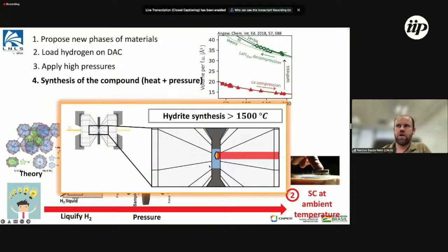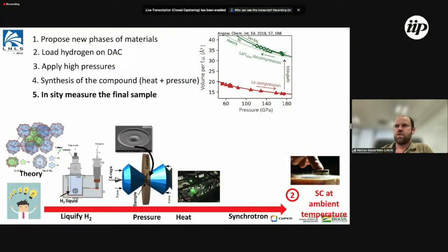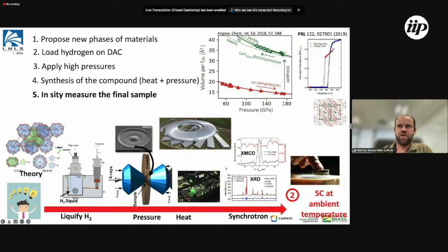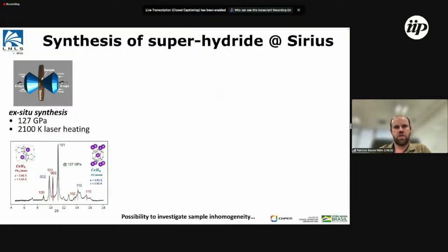We press it, but not only press it, we press and heat with laser. So we put the sample there with the hydrogen, with diamonds, and then put a laser, and we go to extreme pressures and temperatures a little above 1500 Celsius degrees. After that, in situ, we do the X-ray experiments. We can do both X-ray diffraction and X-ray spectroscopy and see how the atomic structure is and hopefully how the electron structure of the material is behaving at that condition.